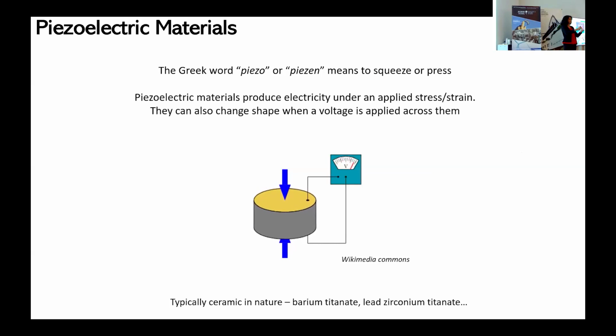So basically, if you squeeze the material or you strain it somehow, there is a change in polarization, which results in an electric potential developing across the material, and you can have an external circuit and cause a current to flow. The reverse occurs as well. You can apply a voltage across these crystals or these materials, and they will change shape. And you see lots of examples in everything from ultrasound machines to gas lighters, where we make use of this effect. And typically, these materials are ceramic in nature.